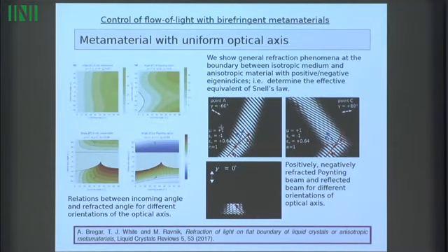So we could talk about some generalization of the Snell law for the refraction of light into these special materials. What we notice is, for the same parameters, but just for different optical axes, for this optical axis, we get all positive refraction, and then here we get this mixed refraction, so positive wave vector, negative Poynting vector, and then for some combinations we get, okay, absorption is not the right thing to say, we get no propagating solutions for the wave vector.